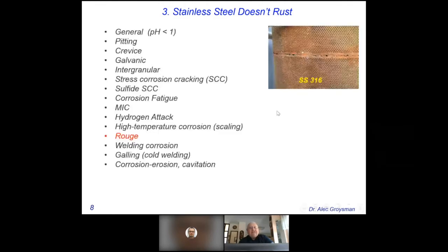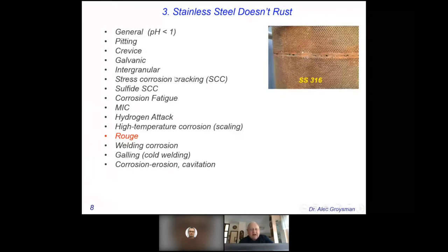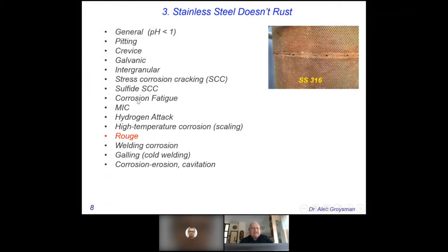The term stainless steel is responsible for another myth, the belief that stainless steel does not rust. In languages other than English, the confusion can be even worse. For example, in Spanish, stainless steel is called acero inoxidable, unrustable steel. We may identify 15 corrosion phenomena that can occur with stainless steel. Wow! And you see pitting, crevice, galvanic, intergranular, stress corrosion cracking, sulfides, stress corrosion cracking, corrosion fatigue, microbiologically induced corrosion, and so on.